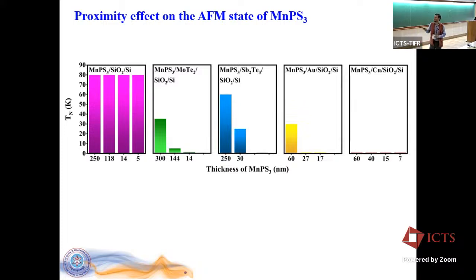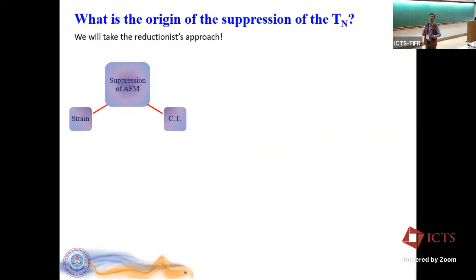Okay, so from all these experiments, we could at least establish to an extent that there is a role of SOC and there is a role of charge density of states. So there are other theoretical models which were also published by then, and we tried to look at whether those are the possibilities. Here we are taking the reductionist approach, and we see if strain and charge transfer could be an important player. Just to remind you, these systems are not metallic. These systems are somewhat insulating. They have a gap of approximately 1.8 electron volt. Okay, so there we believe that charge transfer is not really playing much role, but I'll try to convince you why.